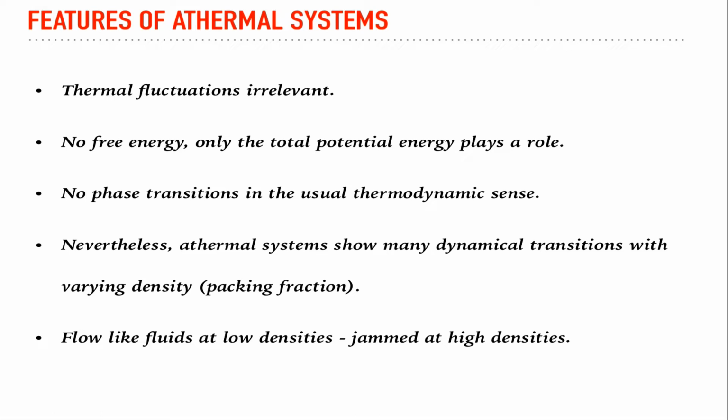But you can still have interactions between particles governed by potential energy, and mainly the properties of such systems are governed by the potential landscape that is coming from the interaction between particles. Because of this, we don't have the usual phase transitions that we see in statistical mechanics, but still you can have very strange transitions where, as I showed you, sometimes the system behaves as a liquid, and sometimes it behaves as a solid, and these are governed mainly by macroscopic variables such as density and packing fraction, very similar to what we see in thermal systems, but the reason why these transitions happen are wholly different. And so these many transitions such as jamming transitions are seen in such systems, and not just that, you can also understand low temperature glasses using many of the techniques that have been developed to understand jammed systems.